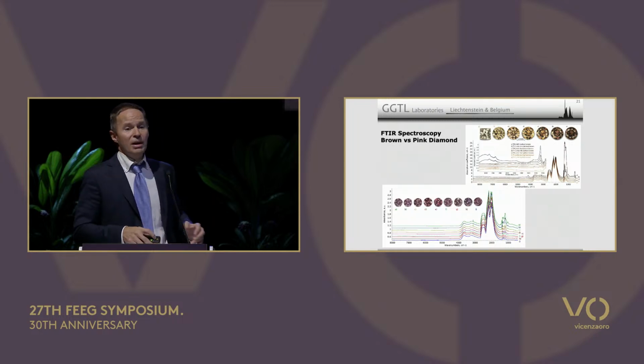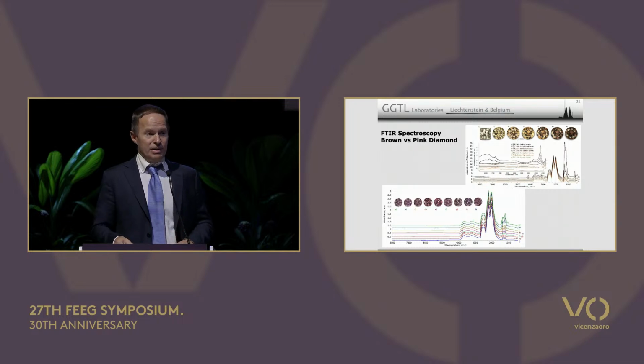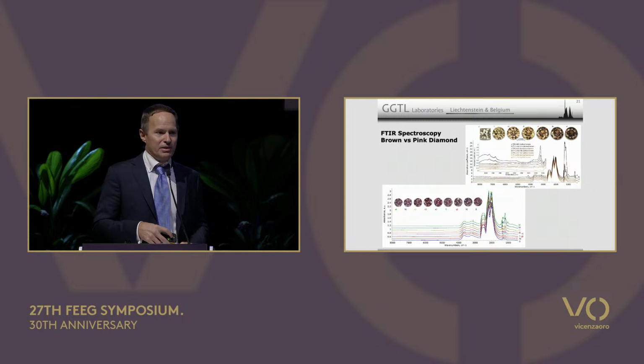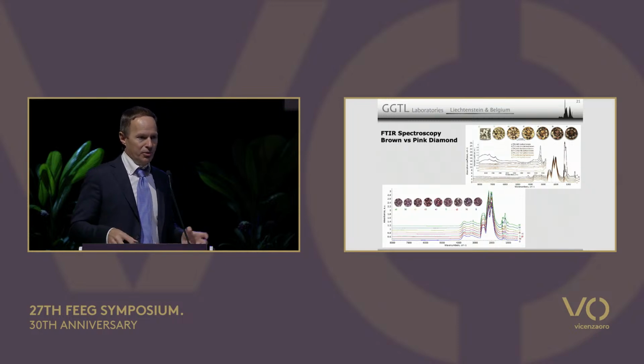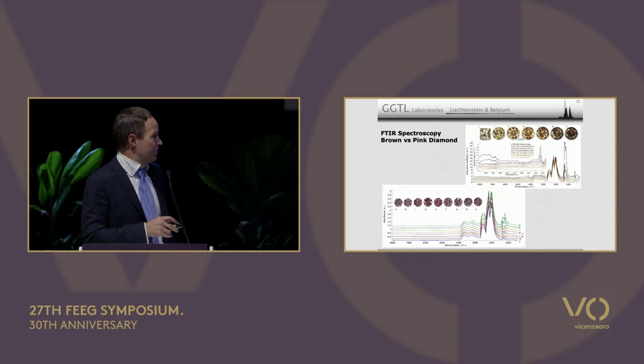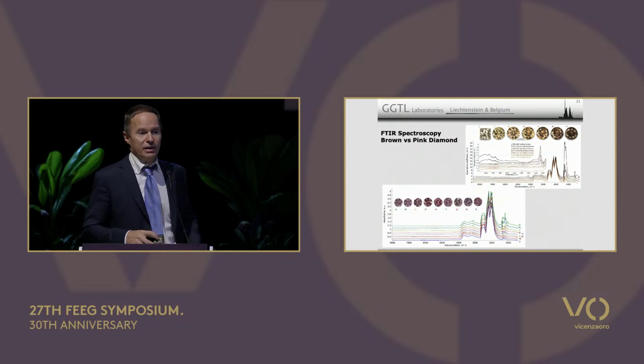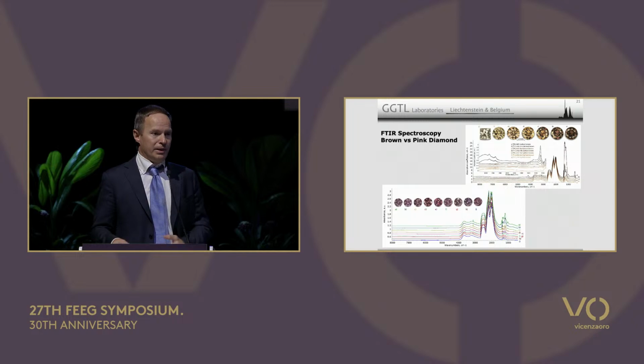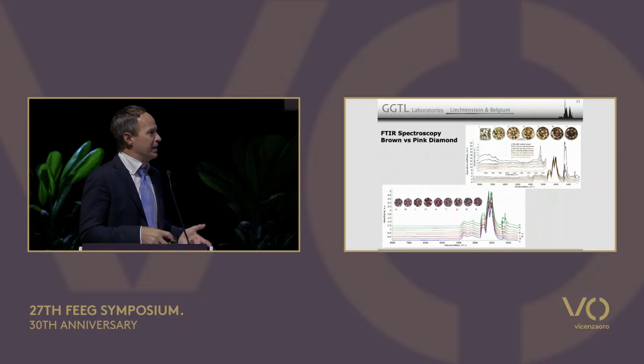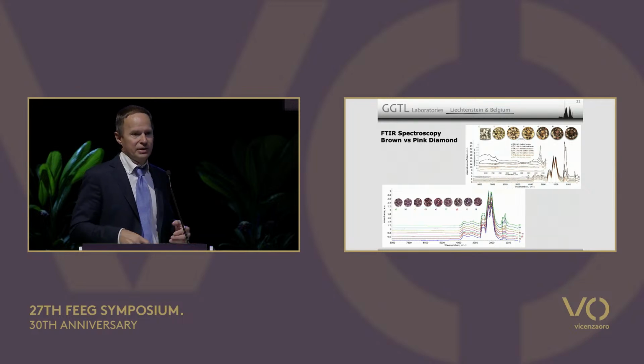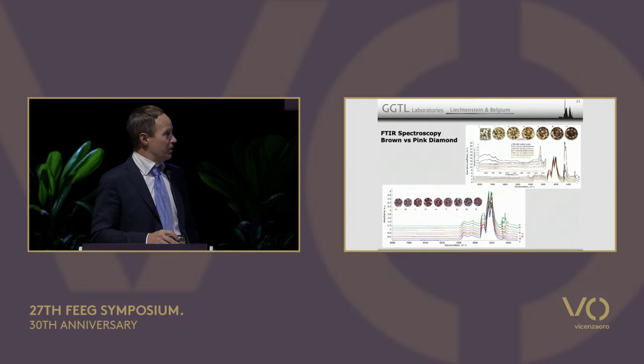Pink diamonds, when they're really pink, have no amber center. If you see orangey pink, you will have amber centers. The amber centers are weak, but many of the so-called orangey pinks from Argyle, for example, contain a really small amber center here. And that correlates straight with some brown lamellae that are contained in the stone, because that's actually what gives you this orangey appearance.